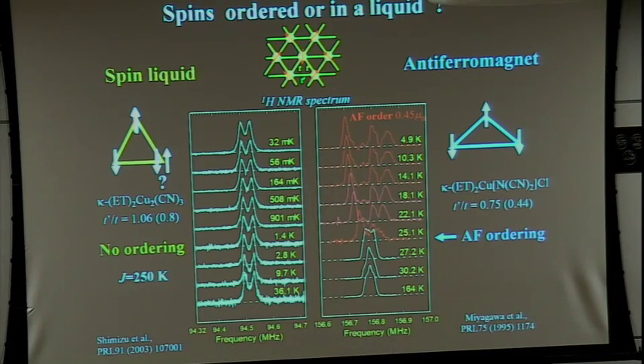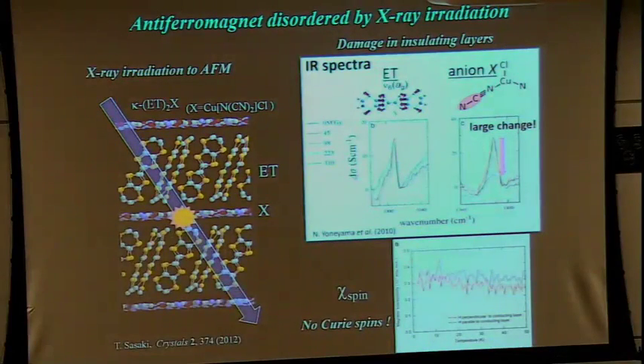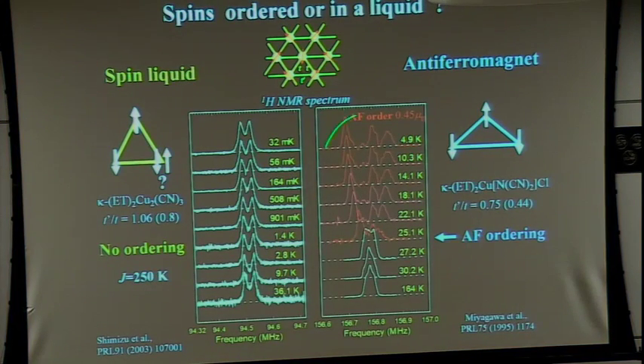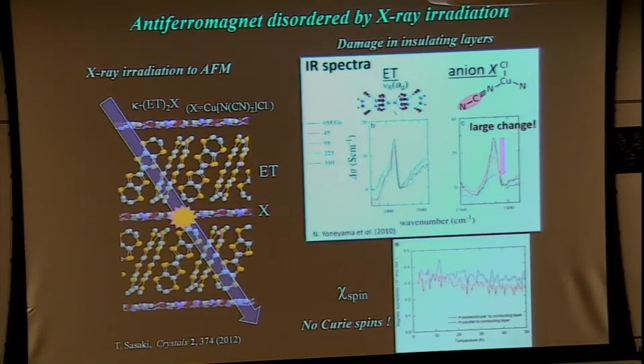Okay, again, let me show the NMR data of two materials. One is antiferromagnetic, where ordering occurs, and the other one is a spin liquid. We can convert this material to this material by introducing disorder. What we did is irradiate X-rays onto the classically ordered state. By examining optical measurements, what occurs under the X-ray irradiation is some breakup of atomic arrangement or chemical bonding in the insulating layers.